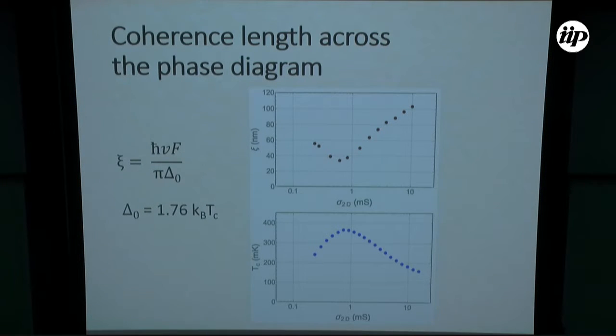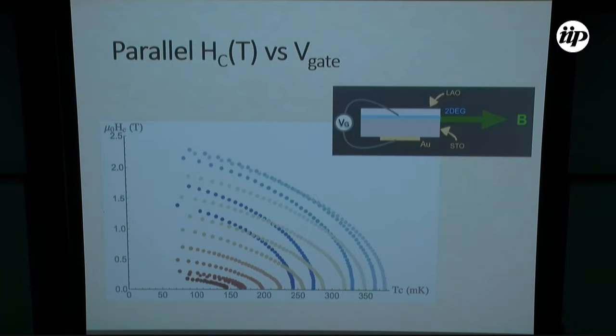Now, if we apply the field parallel to the interface, we confirm that the system remains two-dimensional for all the dopings. So we see this square-root behavior moving from the depletion or underdoped regime, to the optimally doped regime, and then to the overdoped regime. All these curves have the same temperature dependence. What we see is that they are exceeding the paramagnetic limit, the Pauli paramagnetic limit. So in parallel field, we exceed the Pauli paramagnetic limit by a factor of 5. Now, this may